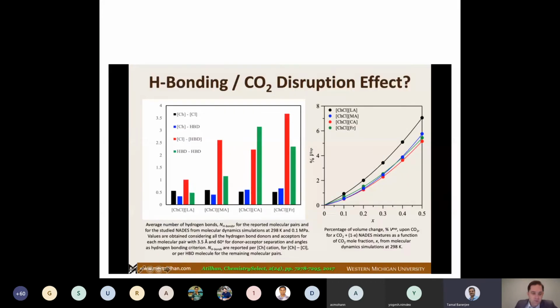Okay. So one of the issues that we also looked at was, we claim that we work with deep eutectic solvent, but when we charge the gas into the system, we don't know whether this charged gas disrupts the eutecticity, which means that the hydrogen bond donor goes one way and the hydrogen bond acceptor goes another. To observe this, we ran molecular dynamics simulations with my colleague, and we observed the hydrogen bonding in the case of choline chloride and levulinic acid, or malic acid, citric acid, fructose.